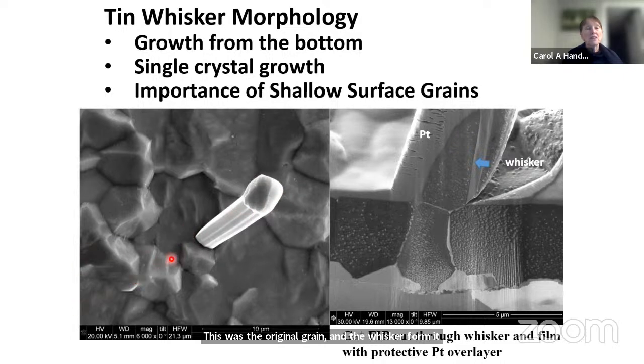So diffusion from multiple grains away from this is happening to relax the stress in the film by the formation of the whisker. So think about this as an extrusion, almost like an extrusion situation. You have accretion of atoms at the bottom, and it pushes it up, and so this grain has this particular configuration. This is a FIB cross section.